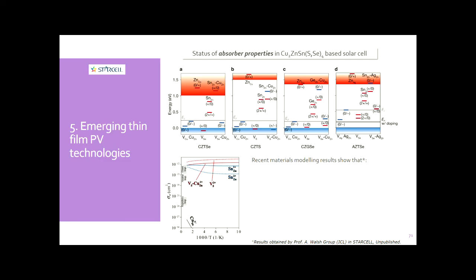As I told you before, all these problems come from the composition of kesterite, but you also have complex interfaces and a large number of defects, deep defects associated to tin, high non-radiative recombination, and very low carrier lifetime characterized kesterite. All bad properties for a solar cell, and a large VOC deficit and efficiency still at the 13% level.